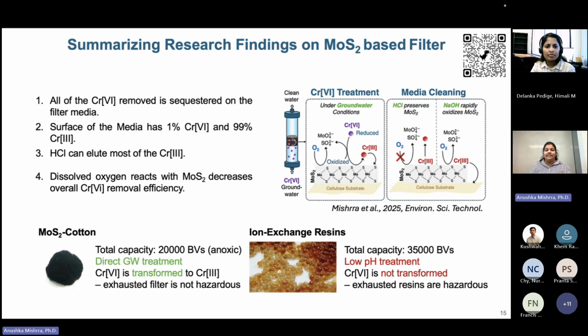So our aim is to create something that can match these bed volumes and not simply be a technology for the sake of it. We could show that under oxygen-controlled environment, we can get somewhere closer to the ion exchange system. However, more work needs to be done to get there.